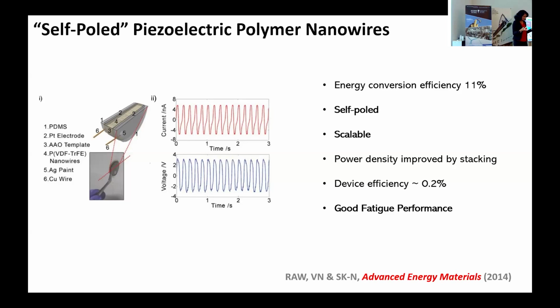So let me explain what I mean by self-poling. Remember I said, ceramics, fantastic, they give you great piezoelectric properties. But even within a ceramic, like if you have a chunk of barium titanate, say, it's still made up of individual grains. And while each grain has a dipole moment or some polarization associated with it, if they're all pointing in random directions, same problem with a polymer. You can squeeze all you like, you're not going to get anything out of it. So what you need is for all the dipoles to point in a particular direction. So then when you apply pressure or strain or whatever, you change the overall polarization.